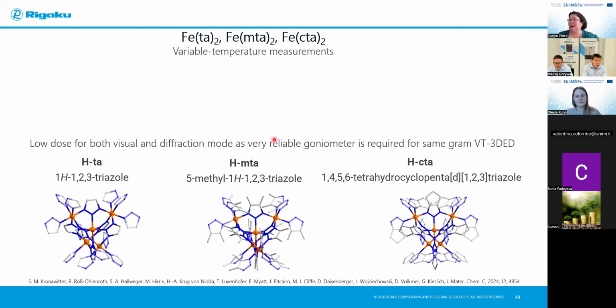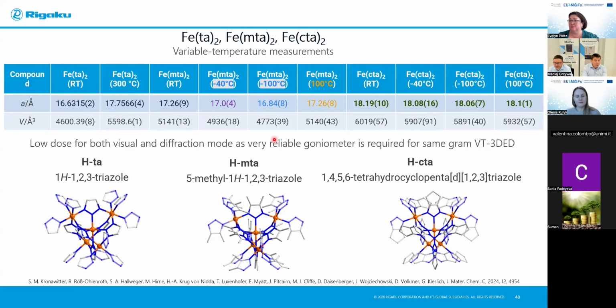But to fully understand this, they need to actually understand how the structure changed during the phase transition, and this was done with 3D ED on a single grain, less than 1 micron. After that, the full analysis of the powder was done, and we could easily find evidence that the middle one still shows a change in volume with the temperature, but it's not enough to provide the phase transition like it happened in the basic version. And then when they exchange to the cta ligand, the stiffness of the framework is so big that it doesn't show any changes in the volume or the unit cell, and they completely eliminated the phase transition.